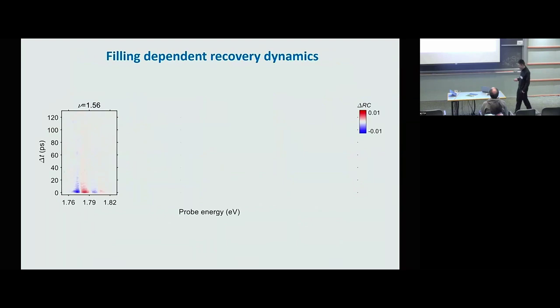Now we are trying to look more quantitatively at the relaxation dynamics of the system. To this end, the typical way is to subtract the background of equilibrium spectra. So here we can see before time 0 there's no signal because it's subtracted. This allows us to directly look at the pump-induced change, or the excitations in graphene, and see how it changes over time. At time 0, once the pump arrives, we see a strong signal, and then it decays over time. So we can directly see how it decays and look at the relaxation dynamics.